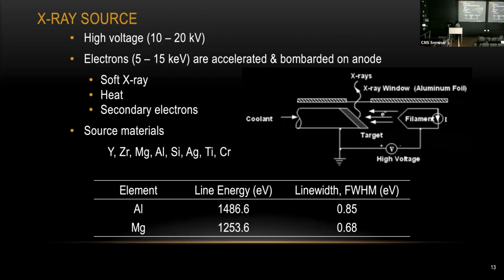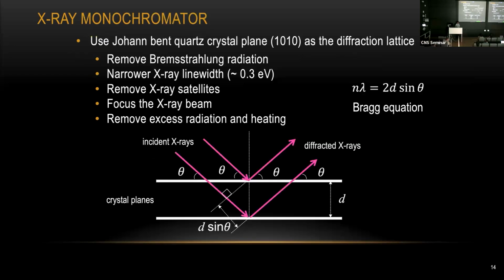But the X-ray coming out from the X-ray gun here is not a clean X-ray beam, so we call it dirty X-ray. There's still a lot of junk in the beam, so we need to do some filtering, and that's why the X-ray beam needs to go through the monochromator, which is simply a kind of quartz crystal plane. By going through the monochromator, we can remove some Bremsstrahlung radiation, which is the main source of background in the X-ray beam when you generate X-rays. We can also narrow your X-ray beam line width a little bit more, to about 0.3 eV. We can remove X-ray satellite peaks, and also we can focus the beam much smaller.